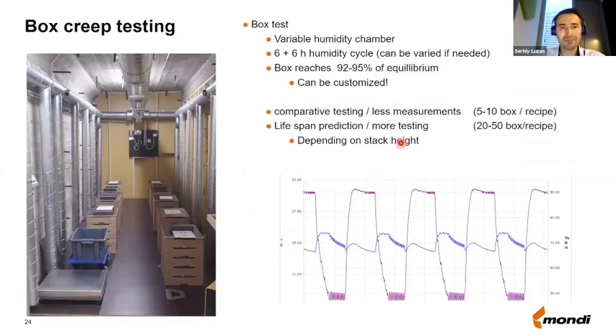So how can we test this creep resistance of corrugated board or boxes? Here you have a picture taken in our laboratory where we do these tests. So you have a very big humidity chamber where you can change the humidity, keeping the temperature as stable as possible. You put the stacks of boxes, you load the boxes to different load, and then you measure the time, which shows you at which time the boxes are collapsing depending on the load. And then you can again build the same relationship between the time and the load. And then for this box, you can quite precisely predict how long the box will hold a given load in